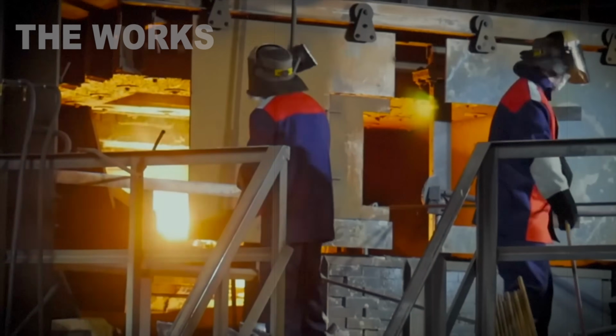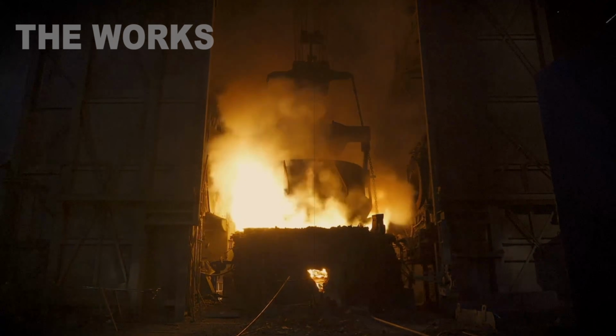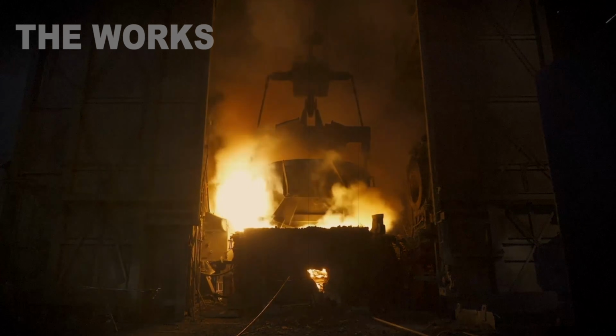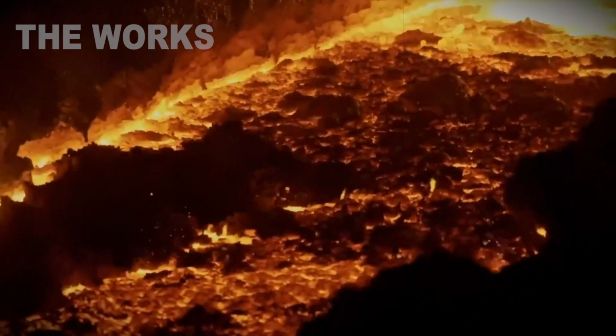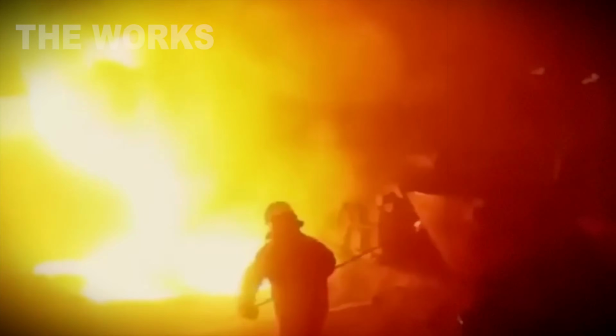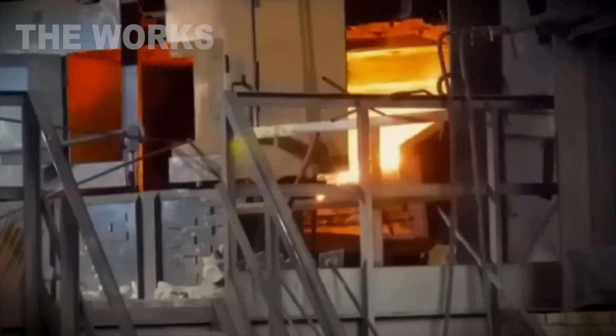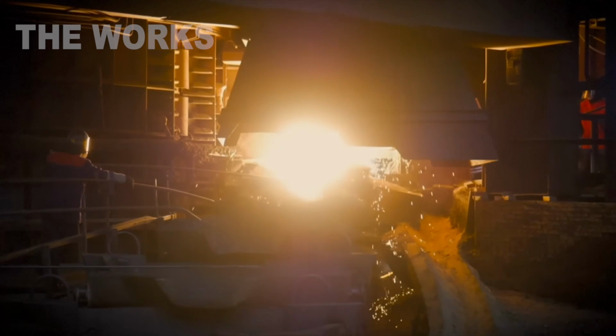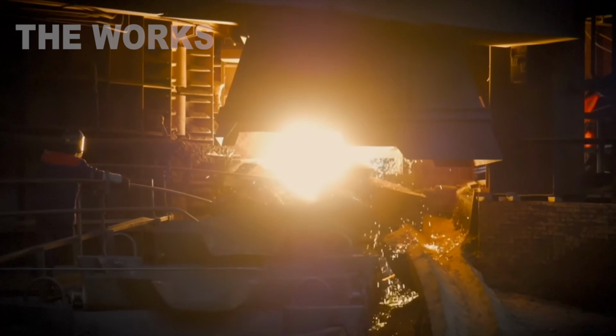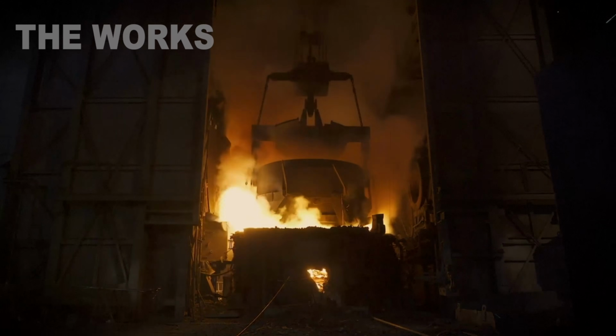Air bubbles will kill the part. Metal fills the mold from bottom to top, pushing air out through the top. After pouring, they don't touch the mold. Cooling is slow, 8 to 12 hours to reach room temperature. Fast cooling means cracks, slow cooling means proper structure.